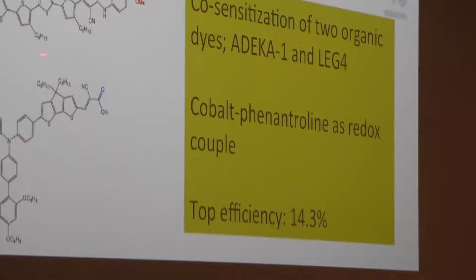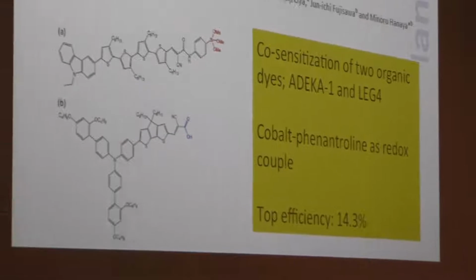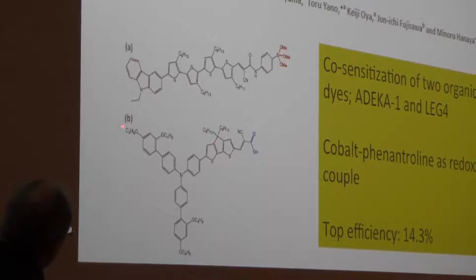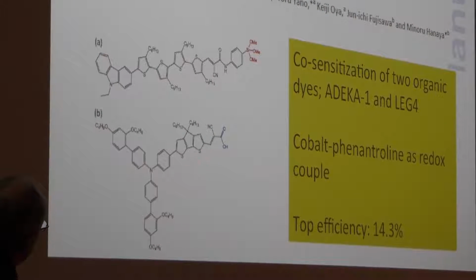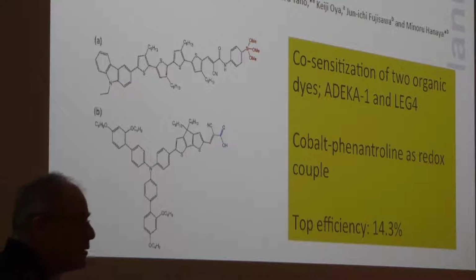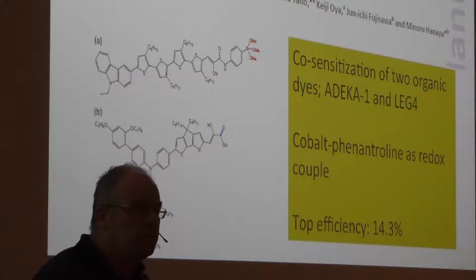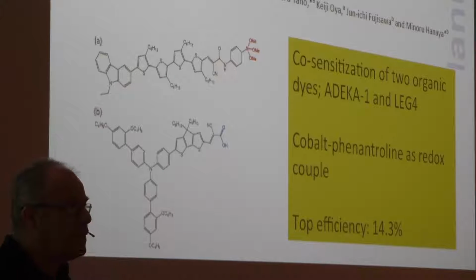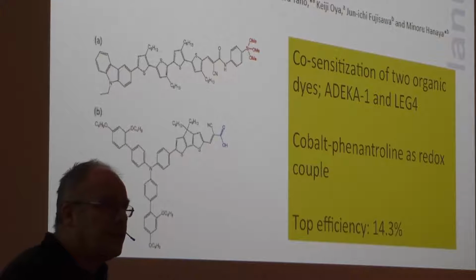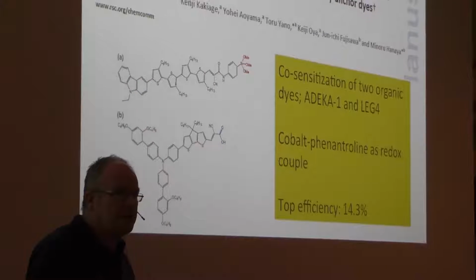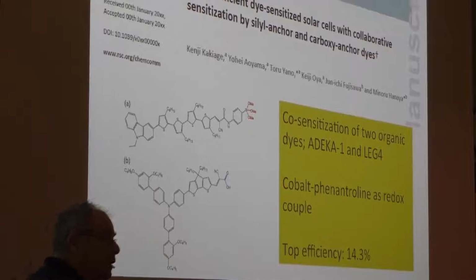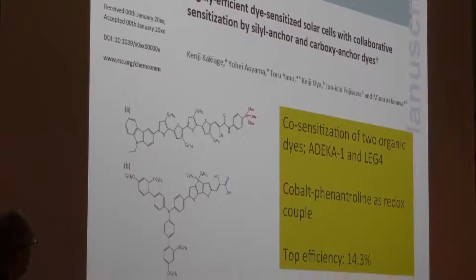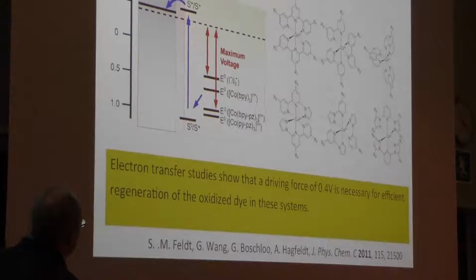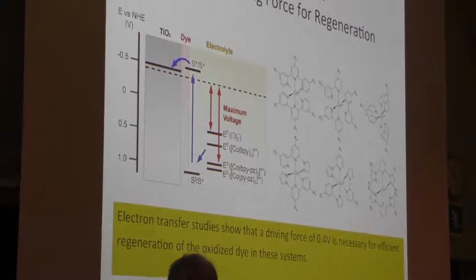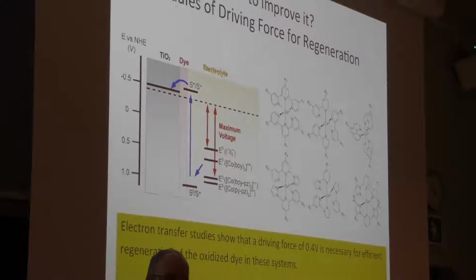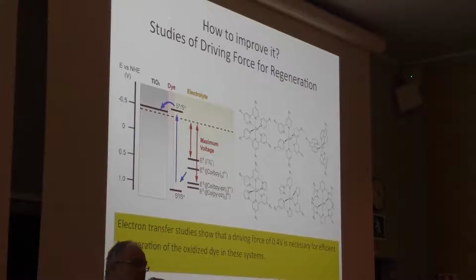It's also interesting, it's a co-sensitized system, we call it. This is their own organic dye, and this is the dye we developed in Uppsala they use. And these two together give this high efficiency. So with the cobalt complex, I would say 13-14% are the published record. With iodide, we have a certified efficiency record of 11.9. Question now, can we take this further? And let's see. The next analysis to do was what is now the driving force we need for cobalt complexes.